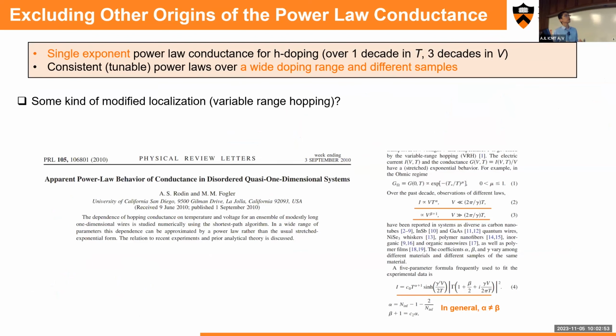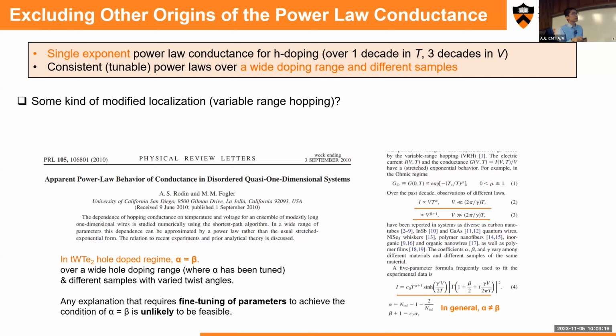And next, I want to show you the early explanation that it might be trivial, coming from variable range hopping or another mechanism, and they propose it might also show power law-like behavior. But in all these papers, summarized by Sasha Fogler, as you can see in the prediction and in this theoretical paper, in general, alpha will be different from beta, which is the power law in the temperature dependence versus the power law in the external bias. But in our situation, alpha is always the same as the so-called beta.